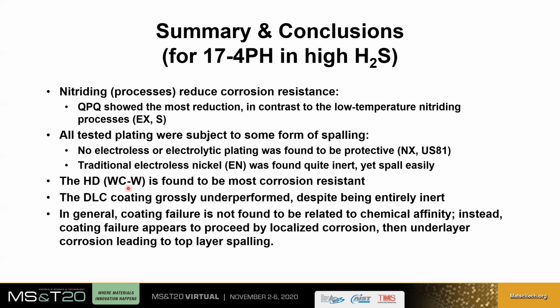Okay? If you look at the tungsten carbide CVD coating, is referred to as HD, it is found to be the most corrosion resistant. Okay? The DLC coating, that's the opposite. It grossly underperformed and was the least resistant. So the takeaway out of all these observations is simply that coating failure is not found to be related to chemical affinity. Instead, coating failure appears to proceed by localized corrosion. And once localized corrosion starts and eventually reaches underlayers, there are reasons to believe that corrosion happens very quickly between a top layer and a substrate or a sublayer, and you end up with delamination or spalling.